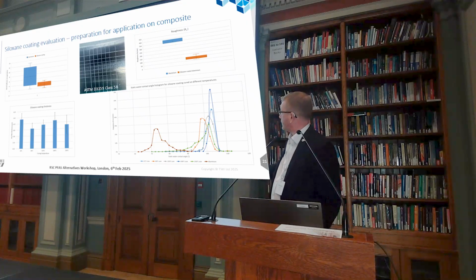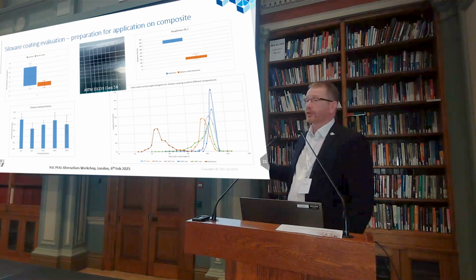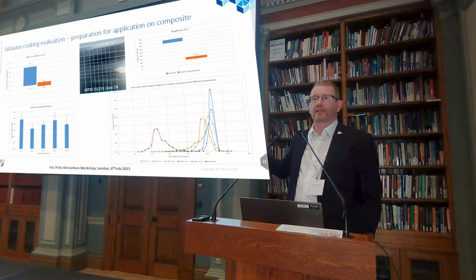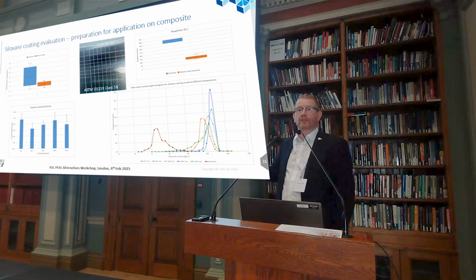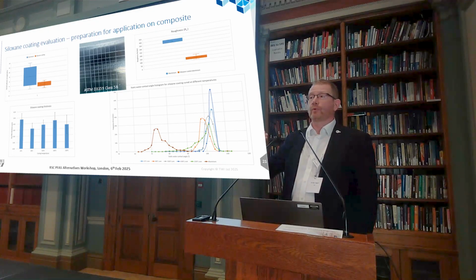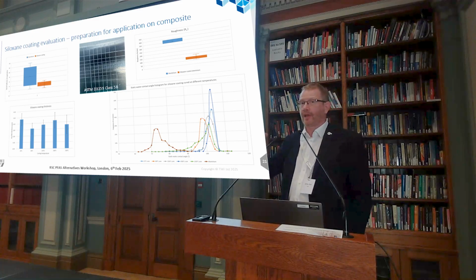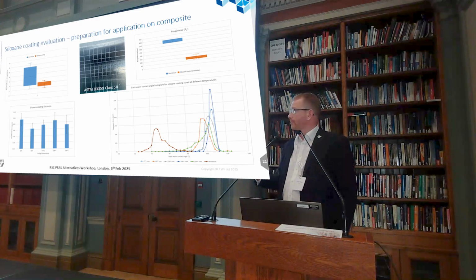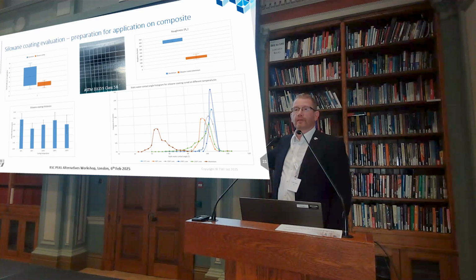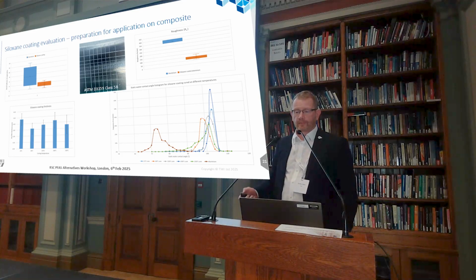And again, just to illustrate the contact angles we can achieve: we can regularly achieve contact angles of 105 and 110 degrees with siloxane-based systems, which, as hydrophobic materials, rival PFAS-based materials. But it is also dependent on the processing that you go through.